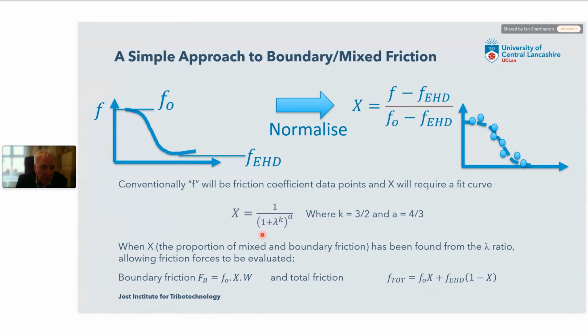So this is the equation for a sigmoid curve. Essentially, we can model this equation by considering just the lambda ratio and these two constants k and a. In our measurements, we found that k is 3/2 and a is 4/3. Once you've got this data, you can very easily then calculate the friction losses in a contact, provided that you know what point in the lambda range your contact operates. And you can get this by predicting the film thickness and dividing it by the square root of the sum of the Rq values squared.